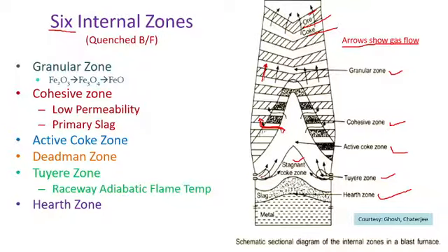Okay, the air that has been given through the tuyeres will not go to the center of the blast furnace. So the center part of the coke will not burn. That will be there in the shape of an inverted V. Okay, that is called your stagnant coke zone. We have also seen the isotherms in the temperature profile of a blast furnace in this inverted V shape.